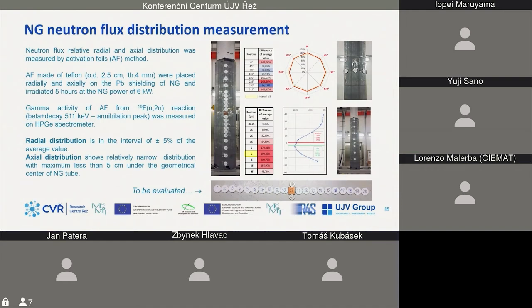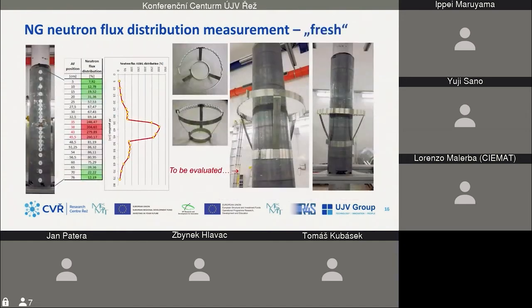Two days ago, we prepared an experiment with more active foils. It is based on the gamma evaluation of activated Teflon foils, the reaction on the fluorine, and later producing the annihilation peak, and the area around the peak is proportional to the energy or the flux intensity. And since this morning, we have the first result.